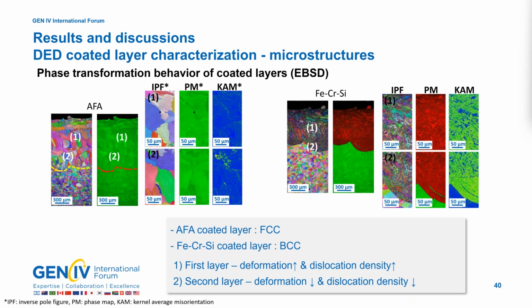To investigate the phase transformation behavior under the selected conditions, EBSD analysis was performed. Consistent with the XRD analysis results, AFA exhibited an FCC structure, while iron chrome silicon exhibited a BCC structure. Additionally, it was observed that the first layer had high deformation and dislocation density, whereas the second layer has relatively lower deformation and dislocation density.